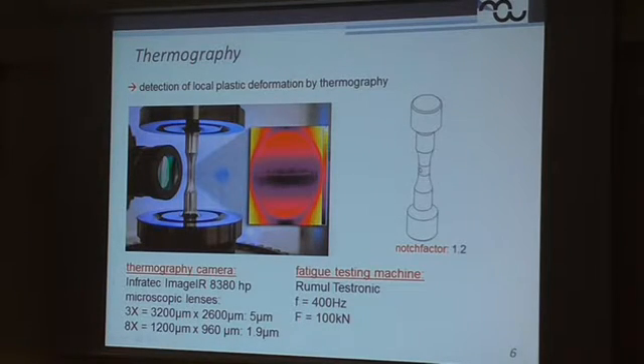And we think that the effective plastic strain amplitude is really low and not measurable on a macroscopic scale, but somehow maybe on a microscopic scale, and therefore we start with a detection of local plastic deformation by high resolution thermography.